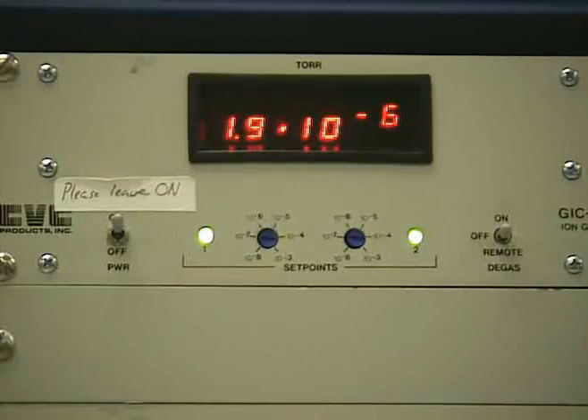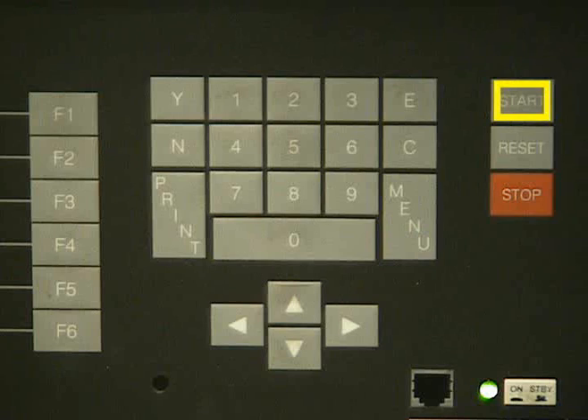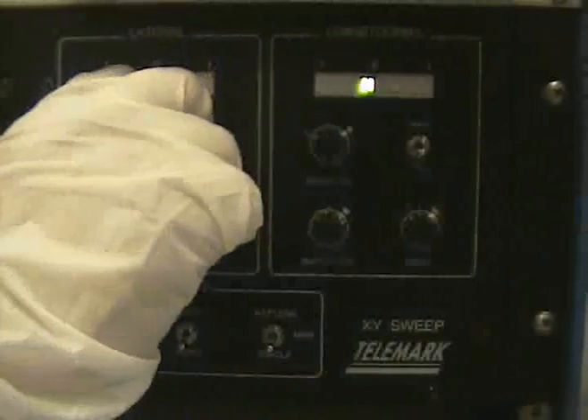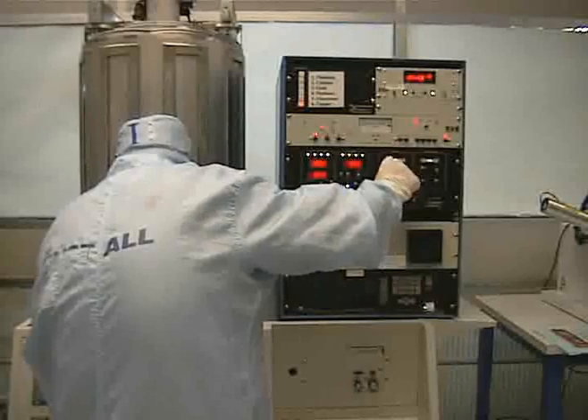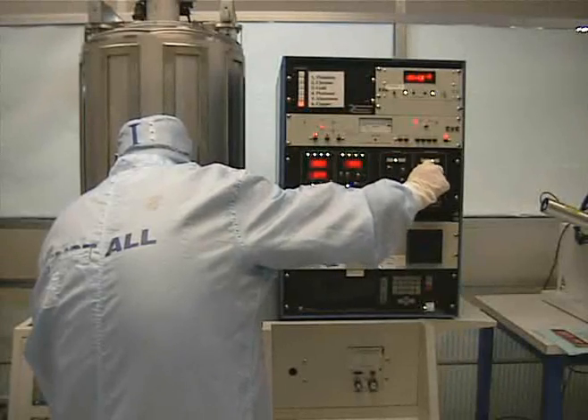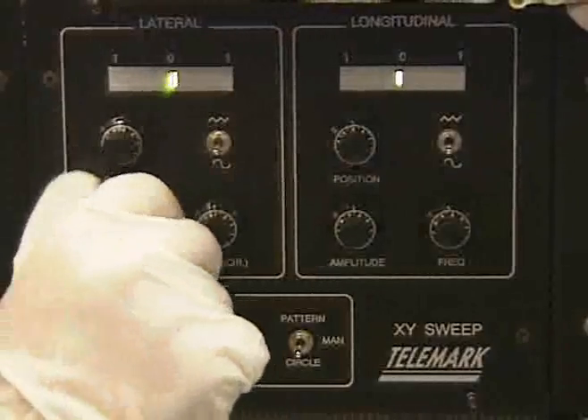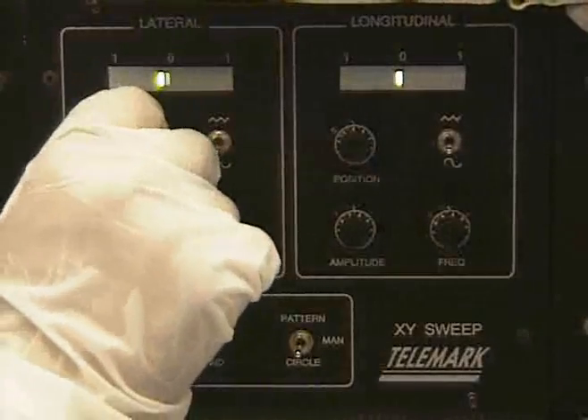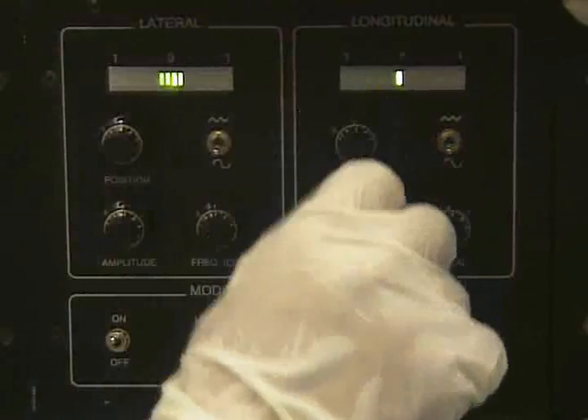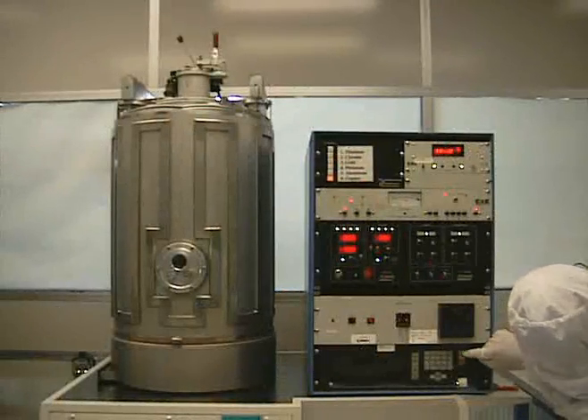Once the pressure has gone down to the desired level, press start on the deposition monitor. We can now adjust our beam. Center the beam using the lateral and longitudinal knobs. You need to be simultaneously looking inside of the chamber and rotating the knobs. Once you have done this, widen the beam using the amplitude knobs. Widen the beam as wide as possible without hitting the crucible. Make sure you are looking at the beam while adjusting the knobs. Doing otherwise can cause damage.